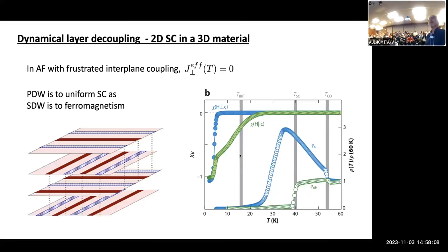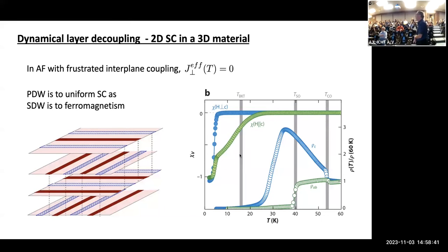Okay, so what does this have to do with the PDW? Well, if the PDW follows the structural motifs of this particular material, what we expect is that the pair density wave will have its ordering vector along the x-axis in one plane, along the y-axis in the next plane. So think of this as being an antiferromagnet, and you can immediately see that the interplane coupling is frustrated. The lowest order Josephson coupling between pair density waves is 0. And so that's our explanation for how you can see this 2D superconductivity without triggering 3D superconductivity.